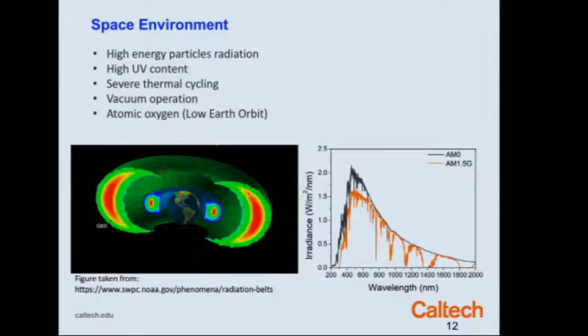In space, we have much more severe weather. We have high-energy particle radiation. We have a high UV content. We have very extreme thermal cycling. We have vacuum. That is good in most respects. If you're close to the Earth, you also have atomic oxygen, which is very reactive. You can also see, depending on where you are, if you're outside the Van Allen belts, which serve to shield the Earth from these high-energy particles through magnetic fields, then we have exposure to the full flux of these particles.